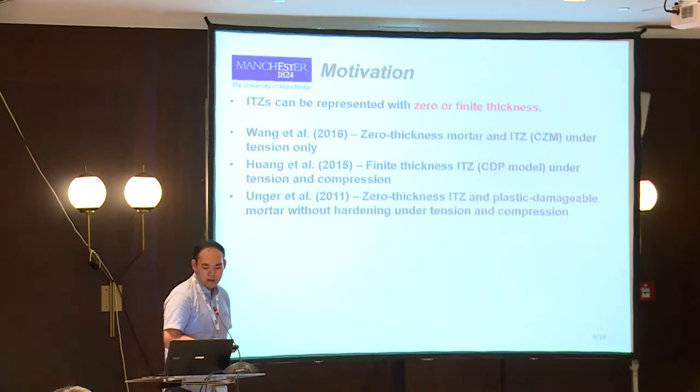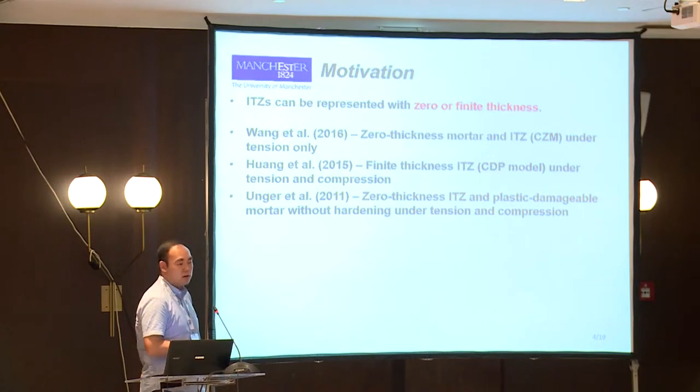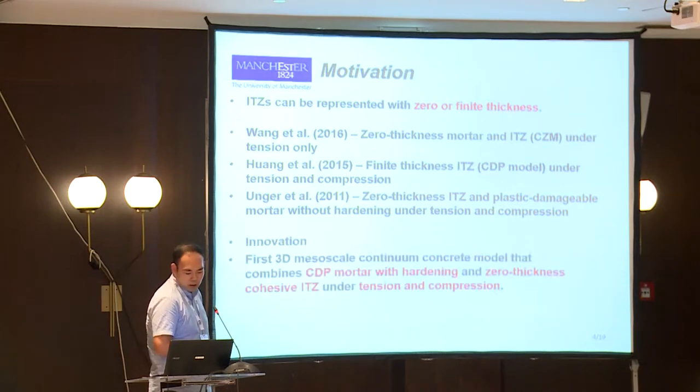Our group has published some papers on models with zero thickness cohesive elements inserted in both mortar and ITZ, but only under tension. And Unger et al. proposed a model with zero thickness ITZ and plastic damageable mortar without hardening. So my model is the first 3D mesoscale model that combines CDP mortar with hardening and zero thickness cohesive ITZ under both tension and compression.